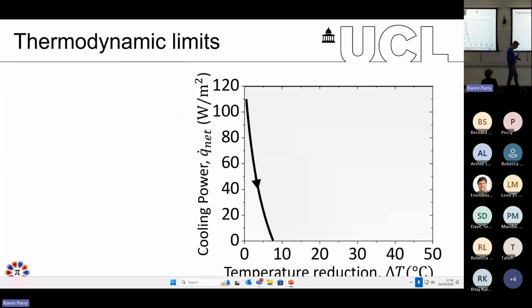Now, one question that comes up all the time is, what are the thermodynamic limits for cooling via radiative cooling? So how far can we go with this process? What I'm presenting in this graph is the temperature reduction below ambient as a function of the net cooling power. The net cooling power is Q-cool minus all the incoming heat fluxes. Now, what happens at the beginning of the process? A surface emits maximum heat, but as its temperature goes down, of course, the heat it radiates reduces up to the point that you have an equilibrium situation. The surface reaches a steady state when the outgoing heat flux balances out the incoming fluxes. This is where the surface attains its final temperature.